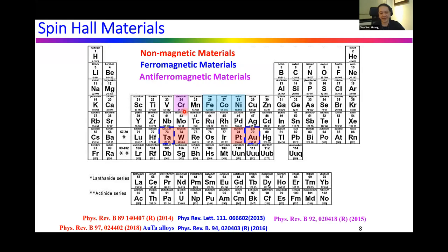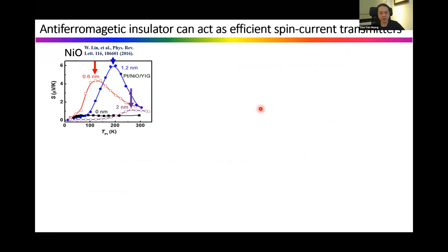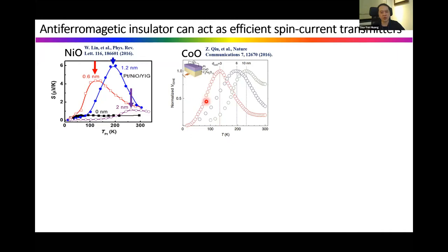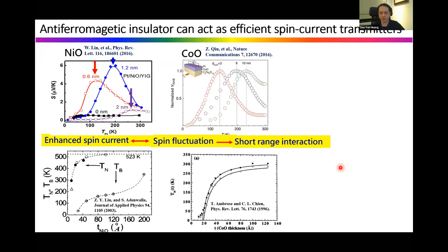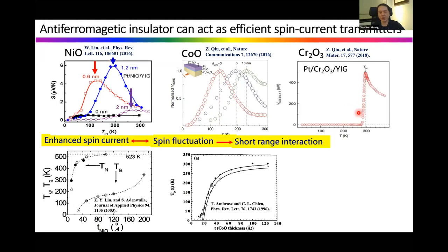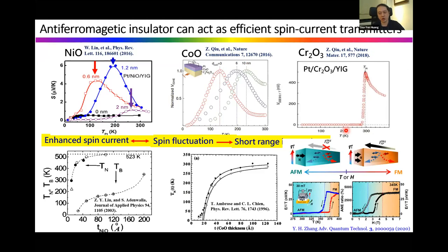This is the main topic of my talk: 3D magnets. It has been reported that spin current excited by spin Seebeck and spin pumping can be significantly enhanced through the insertion of a 3D antiferromagnetic insulator, such as nickel oxide and cobalt oxide. However, the thickness of antiferromagnetic insulator cannot be too thick, where the Néel temperature is even below room temperature. Therefore, this enhancement is attributed to spin fluctuation, which shows a short-range interaction. A similar but more significant result was reported in chromium oxide (Cr₂O₃). This also inspires us to demonstrate a high on/off spin current switch ratio in iron rhodium by a first-order phase transition between ferromagnet and antiferromagnet.